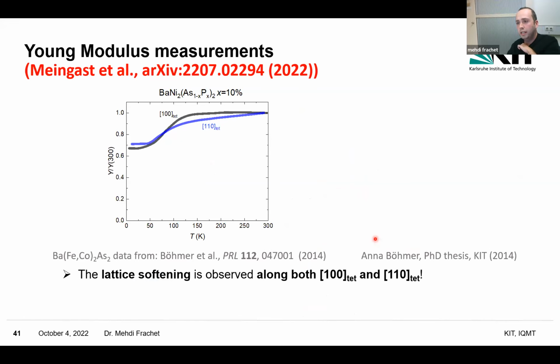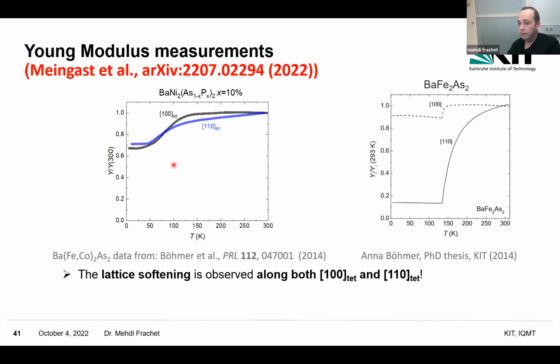Christophe Meingast has done more measurements on this 10% barium nickel arsenide doped with phosphorus. You can see the Young modulus along the 100 axis in gray and along the 110 axis in blue. What you can notice is that there is a lattice softening, but it is observed along both directions and with quite the same amplitude. That's quite different, for example, to what was observed in barium iron 2 arsenic 2, where the softening is much more pronounced along the 110 axis because it's dominated by this C66 elastic constant, which is the soft mode of the transition. So in the nickel case, in this 10% barium nickel arsenide phosphorus, it seems to be more complicated.